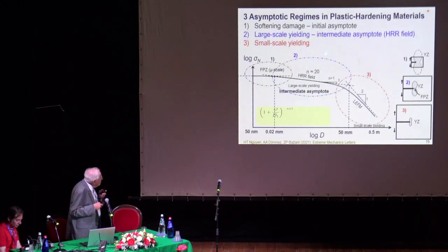Now, this analysis gives a more complete picture. I showed the basic picture, horizontal asymptotes, asymptote size 1/2. Now, because of large-scale yielding in a small structure, you have intermediate asymptotes, which actually span three orders of magnitude. Intermediate asymptote is a concept invented by Grisha Barenblatt recently. And so we have three transitions.